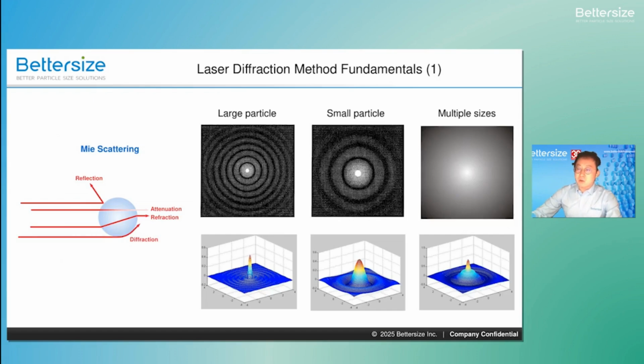To measure these particles accurately, we rely on laser diffraction and Mie scattering theory. The core rule is simple. Large particles scatter light at narrow angles, creating tight, intense rings, while small particles scatter light at wide angles, creating broader, diffuse patterns. By capturing these diffraction rings, like the ones you see on the right, our detectors can mathematically construct the exact size of every particle in your mixture.